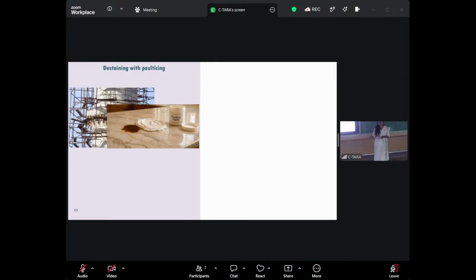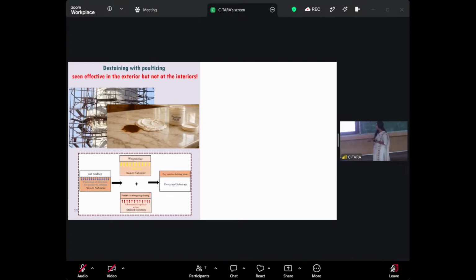This is theory, and it's by capillary suction. Practically, this would happen only if the paste pore structure is much smaller than the inside substrate pore structure. Otherwise, that capillary suction wouldn't happen. So this was being done in the Taj Mahal for many years. And if you go there, you will see that the exterior is very white, especially after this process. But the interior is still yellow. So it works on the outside, but it doesn't work on the inside.